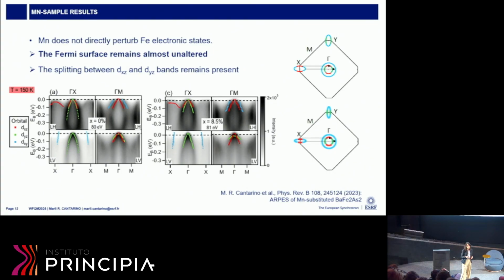So when we see the electronic structure, this is a cartoon with the biggest effects that we see at the paramagnetic temperature. What we see is that the hole pocket sizes are almost unchanged. The only difference we could actually see was that the electron pocket was getting a bit shrunk in one direction, so not isotropically, and all the bands are getting broader. But this is somewhat incoherence because of the doping of the system.